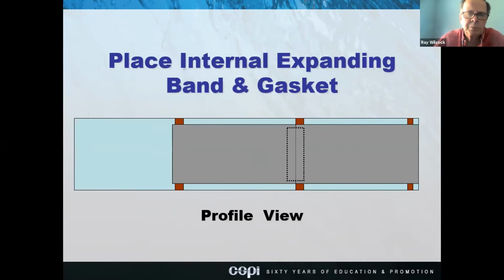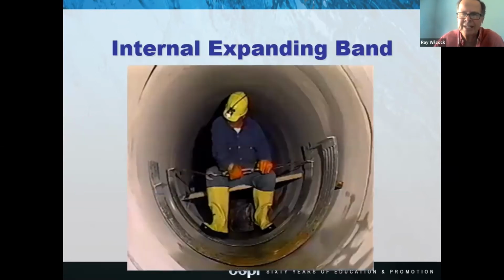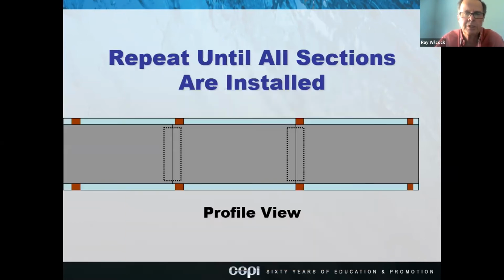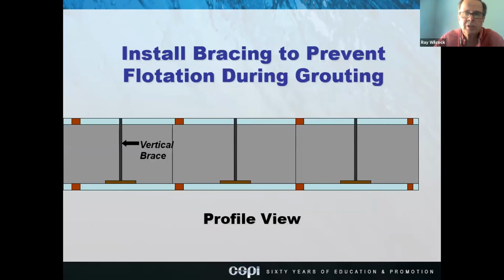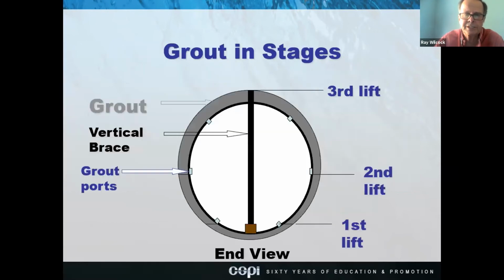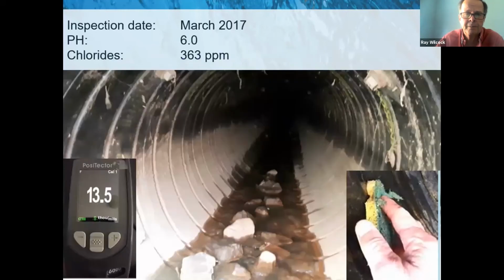Then we placed internal expanding band gaskets on the inside. Here's a picture of what an internal expanding band looks like. That would be going right around the inside of the pipe. You repeat that until all the sections are installed. You install the bracing to prevent flotation during grouting, as you can see there in that vertical bracing. And then you grout in stages. We did a first lift, a second lift, and then a third lift. You can see the grout ports there in that picture with a vertical brace down the center.